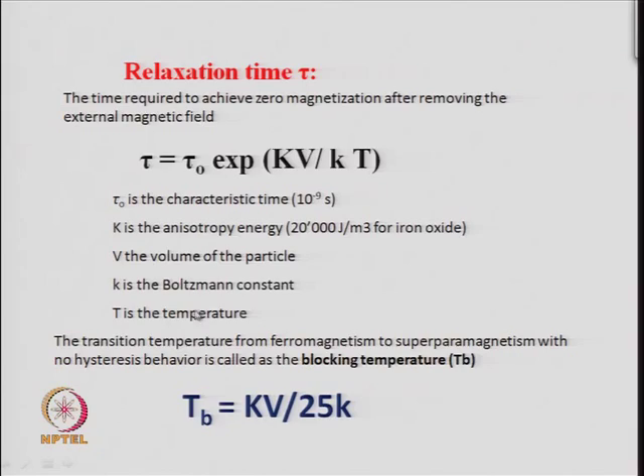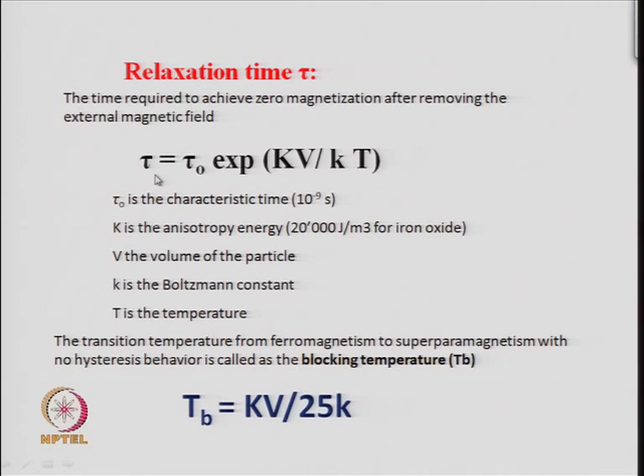Then the blocking temperature, which is also very important, that is the temperature where the ferromagnet becomes a superparamagnet, that blocking temperature is also related to this anisotropy energy. So, larger the anisotropy energy, larger is the blocking temperature. And so, the blocking temperature and the relaxation time are more or less related in this manner. That is, if you keep other things constant, then the material with a high anisotropy energy will have a high blocking temperature and will also have a large relaxation time. So, blocking temperature and relaxation time are that way related.